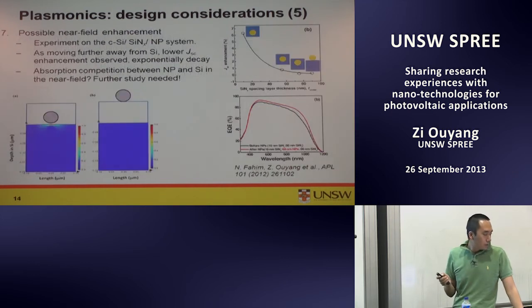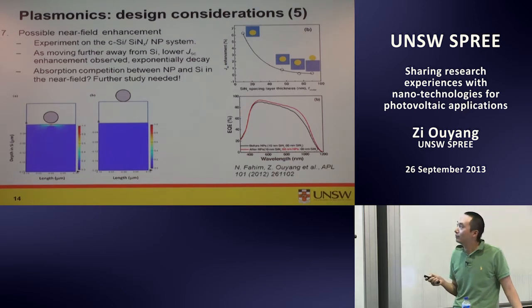So the last thing I will talk about in plasmonics is possible near field enhancement. What you can see is the silicon, the silicon nitride and the nanoparticles. When you move the silver nanoparticles closer to the silicon substrate, you can actually see the boost of the near field at the surface. So we think that might be a good thing.